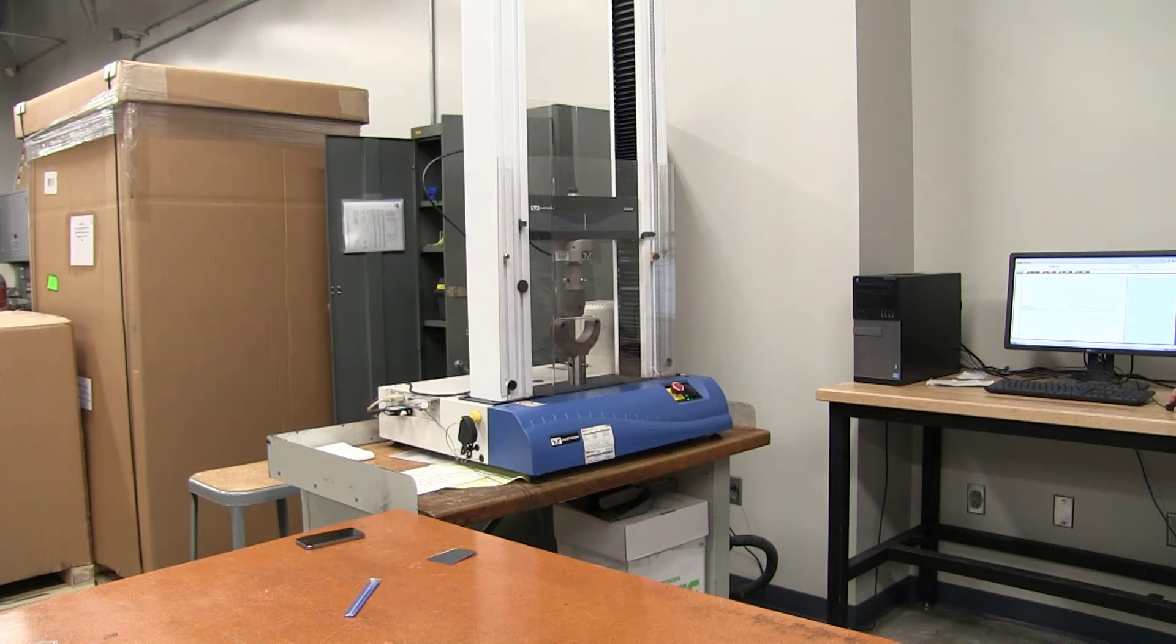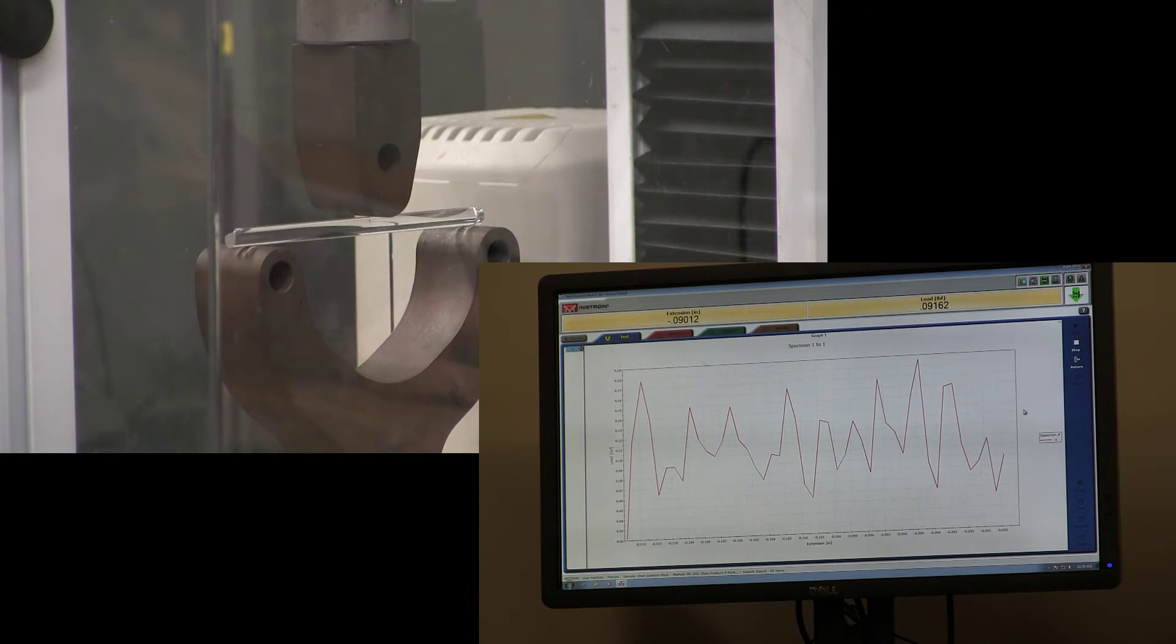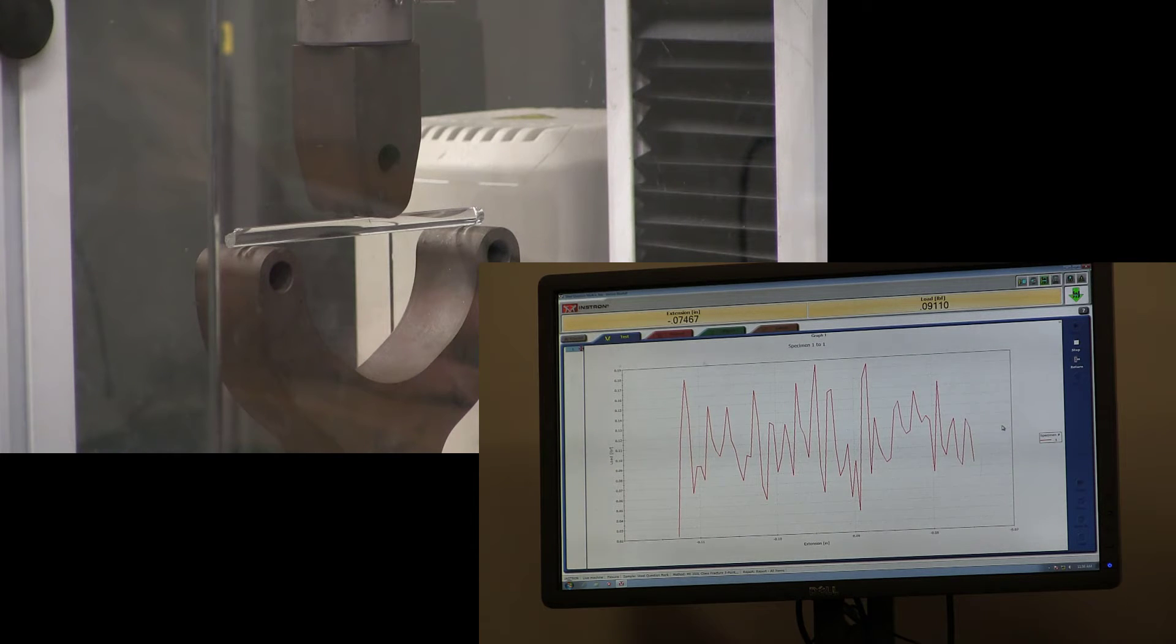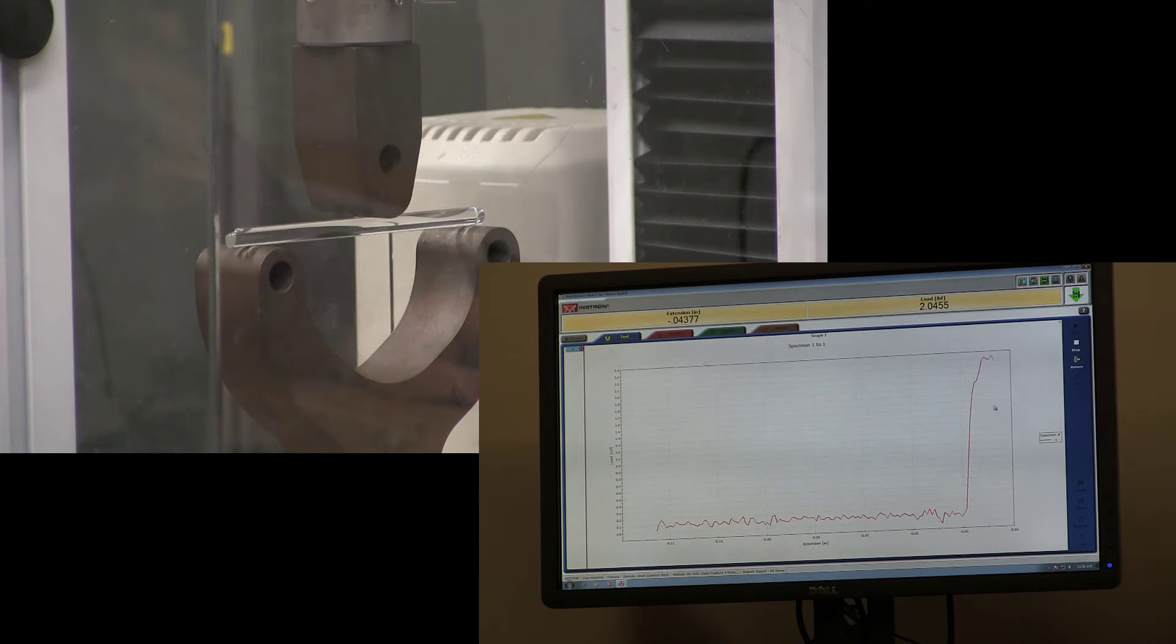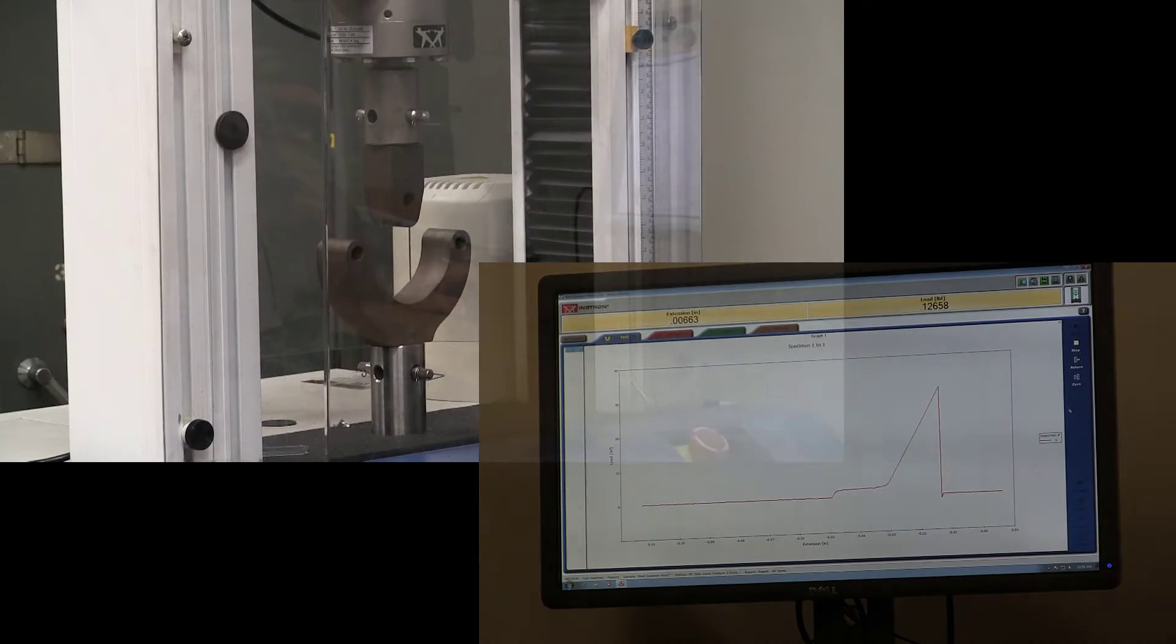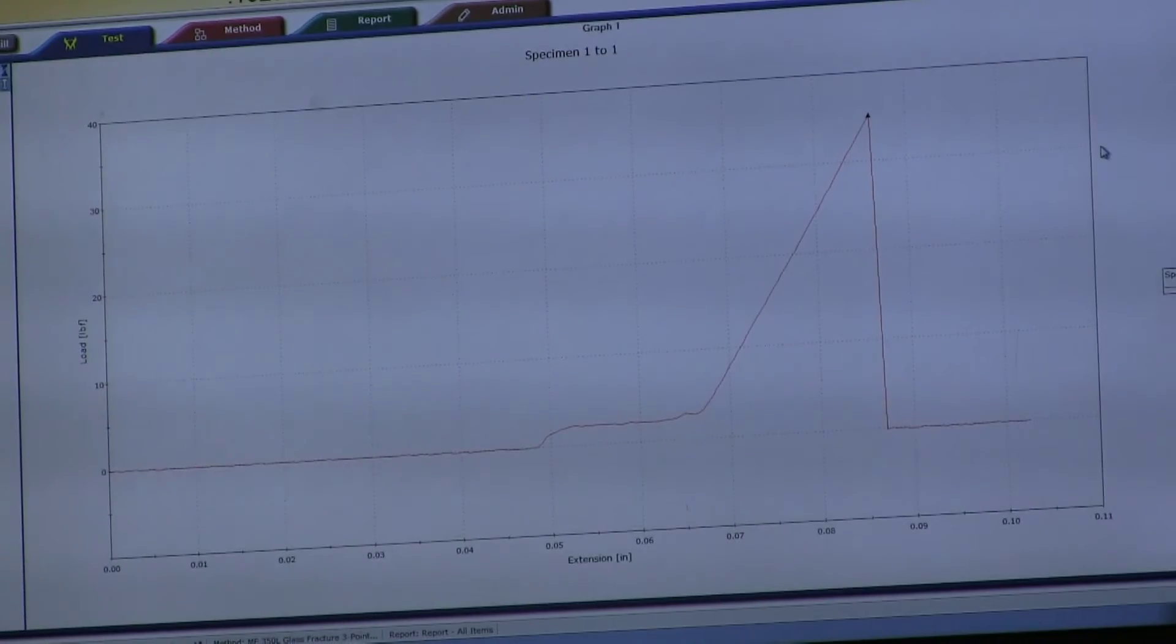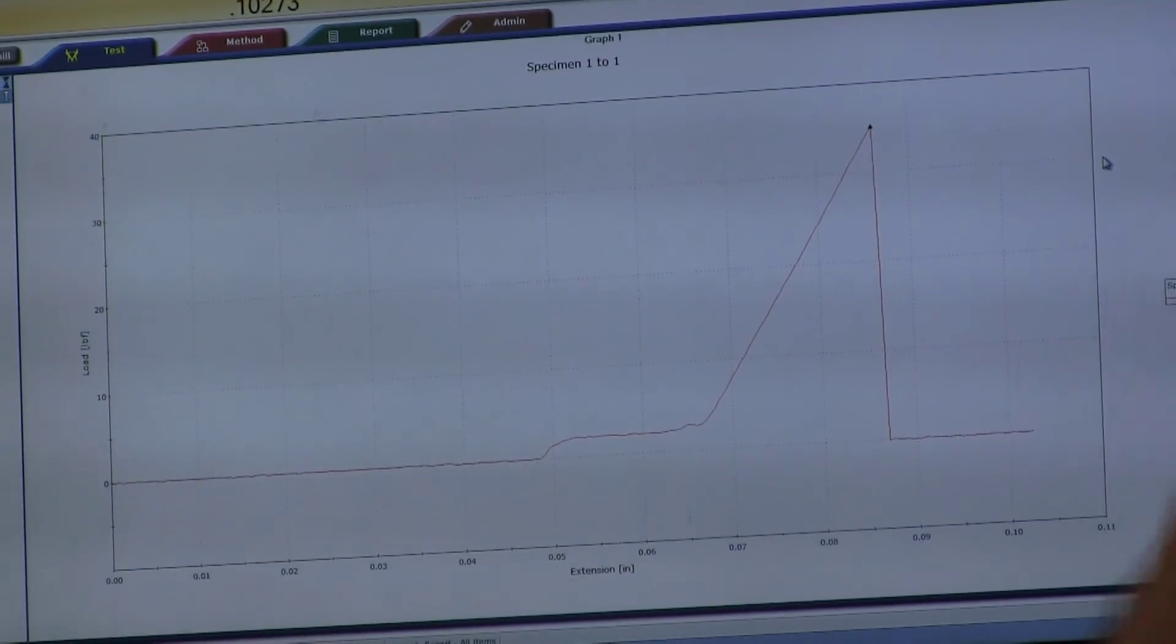And by the time you get to the point of fracture, that little artifact is no longer. So I'm going to plot the load displacement graph. Let's run the experiment. We're seeing jagged lines over here at first, because we're not actually in contact with the specimen, and then the load will go up. So we went up to about a couple of pounds. Now it's going up sharply, and this will be fractured. Okay. And so I'm going to push this off. And the maximum load there was about 35 pounds or so, and as you saw, the glass fractured...